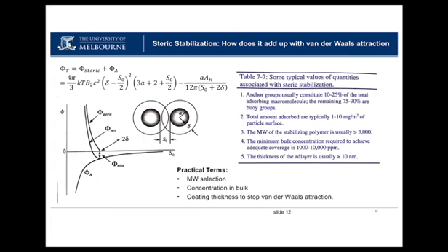There are some great gold sols in the British Museum. They're in Rutherford's lab, in Faraday's lab. They're gold particles that were citrate stabilized, and so they had a charge on them and a van der Waals force. And if you calculate the stability, they should be stable for 1,000 years. And so they're still stable today, and Faraday put them in his lab over 150 years ago. I think it's about 150 years ago. And these gold dispersions are still stable. But the real reason they're stable is he added a little bit of guar gum, so they're sterically stabilized.